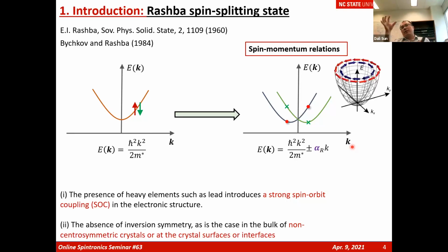If you look at it from the top of the electronic state, you see 2 spin contours, the internal contour clockwise and the outside one counterclockwise, with all the spin orientations locked to momentum space. In this case, it usually contains two contributions, two terms. One is the Rashba term with all the spin orientation directions in the xy plane, and you will also have another term called the Dresselhaus effect.